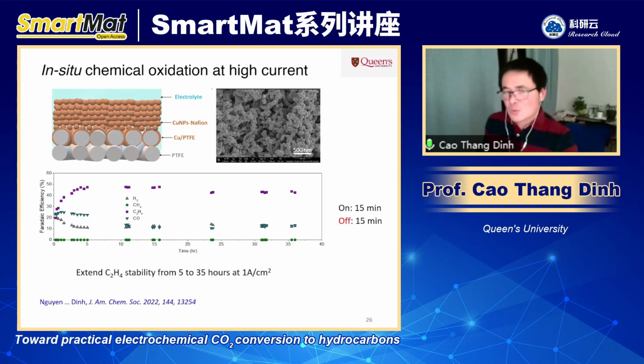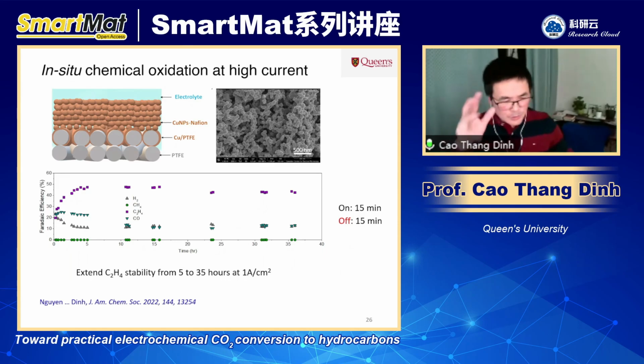The hypothesis worked, and running the on-off can help with improving the stability of the system. But we could not run it longer. Right? We want to run for a few hundred hours. We want to run 1,000 hours, but we can't. We need to stop at 35 hours. And the reason for that is because of the salt formation.